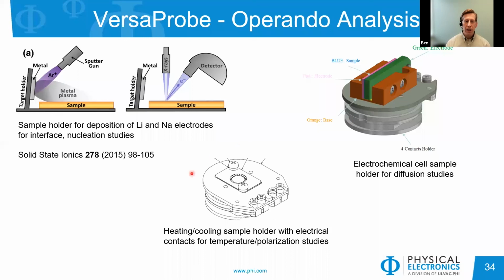And lastly, we have a special sample holder here showing that you can heat and cool. So we can go down to, I believe it's -140°C, up to, in this case, 600°C, and there's another special sample holder that would go up to 800°C. So you have quite a wide range of temperatures that we can use for acquisitions. You can also use these terminals to attach leads to your sample, and then there are electrical feed-throughs that allow you to do electrical biasing in the chamber.